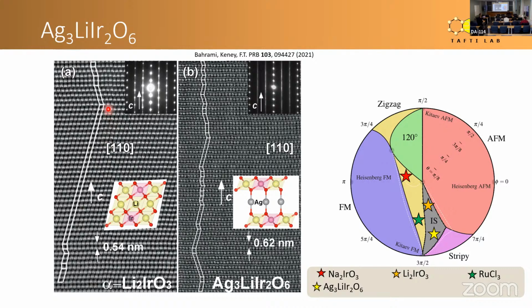However, every now and then you see a stacking fault, in the sense that the direction of stacking changes. And of course, these are layered materials, so it is expected for them to have stacking faults. But you see that in the new material we made, silver lithium iridate, the stacking faults are even more prevalent than in the parent compound.